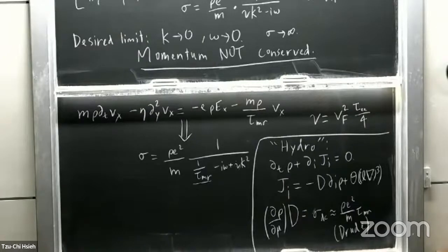So if you take copper, for example, at room temperature, then the theory that describes thermalization in copper is diffusion equations. Actually, it can be a bit more nasty if you remember that electrons interact with a very long-range Coulomb interaction, but sweep that under the rug, and you would have two diffusion equations, one for energy and one for charge. Copper does not have viscous electron flow. For that, we'll need to talk more carefully about what materials may be so clean, and effectively have this tau MR so big, that you can see viscous hydrodynamics kick in. That's the next thing I'll discuss.